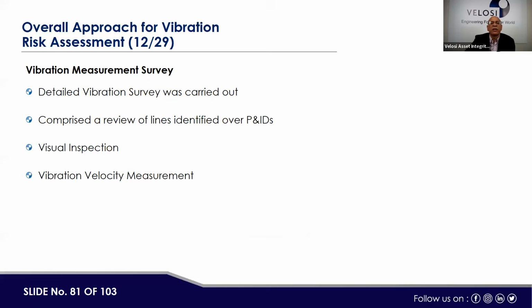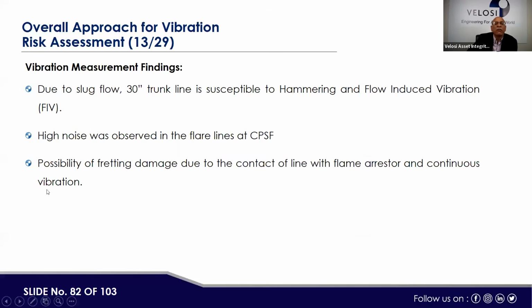Here, a detailed vibration survey was carried out, comprising review of the lines identified over the P&IDs, visual inspection, and vibration velocity measurements. Due to slug flow, the 30-inch trunk line is susceptible to hammering and flow-induced vibration. You can see the 30-inch trunk line was having this problem. High noise was observed in the flare line of CPSF. Possibility of fretting damage due to contact of the line with the flame arrestor and continuous vibration. This is when the pipe is directly supported on the metal.